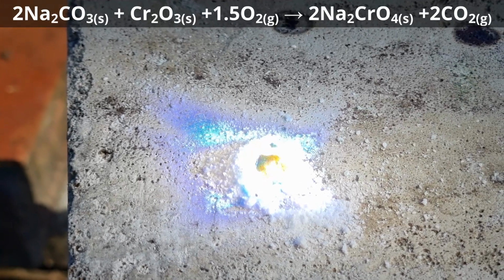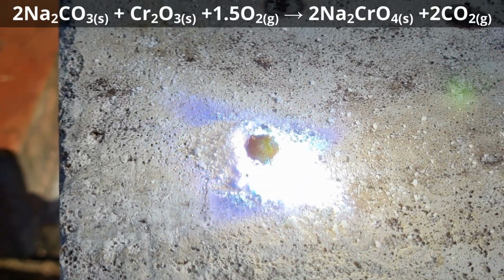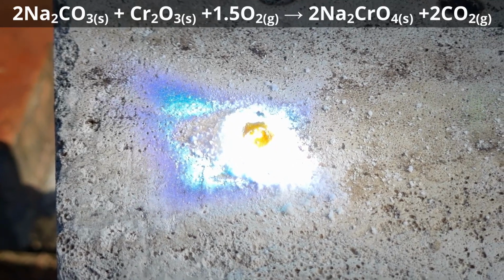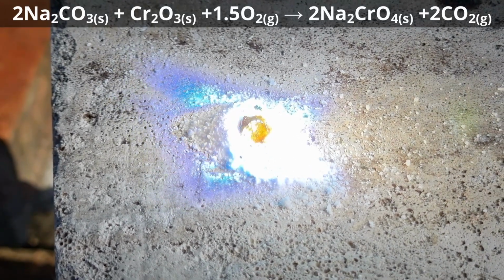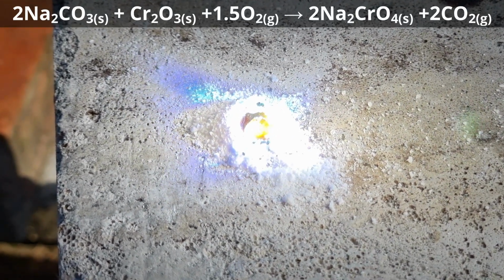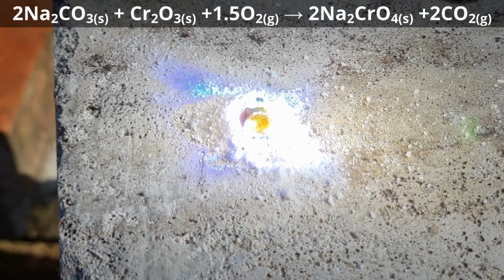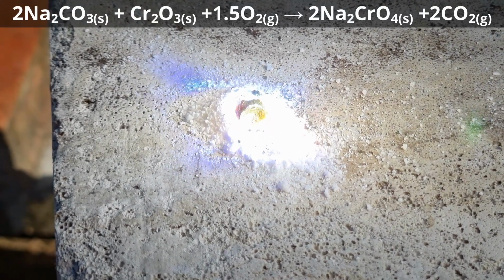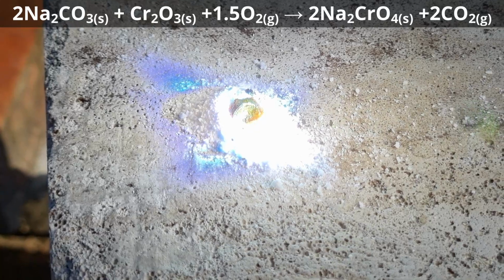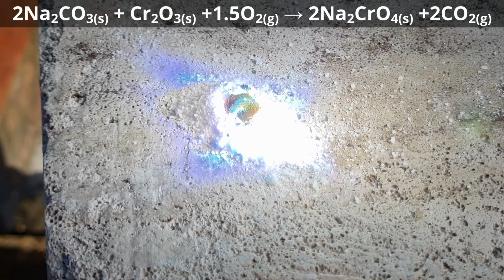As you focus the sun's radiation, the chromium oxide heats up rapidly, which in turn transfers heat to the white carbonate. This gives it sufficient kinetic energy to allow diffusion between the two solids, forming sodium chromate at the interface. In this scenario we have used an excess amount of sodium carbonate, which acts as a crucible to prevent contamination from possible side reactions with the tile. This is also sometimes referred to as a skull crucible method.